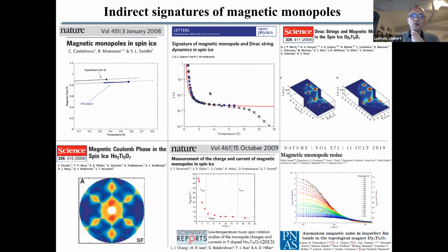So all of this is about magnetic monopoles, magnetic charges, and there have been several papers over the years since 2008 trying to measure this magnetic charge, either with the dynamics, or with neutron scattering, or with mu-SR, or even with very high quality SQUID measurements, measuring the noise of these magnetic monopoles as they move in the sample. But the thing is, all of these measurements are indirect measurements. So they are consequences of the monopoles on the dynamics. They are measurements of the kind of Dirac strings, you have monopoles and the correlations they create in the system. But it has not been possible so far to really see a magnetic monopole and to see the magnetic charge in experiments.